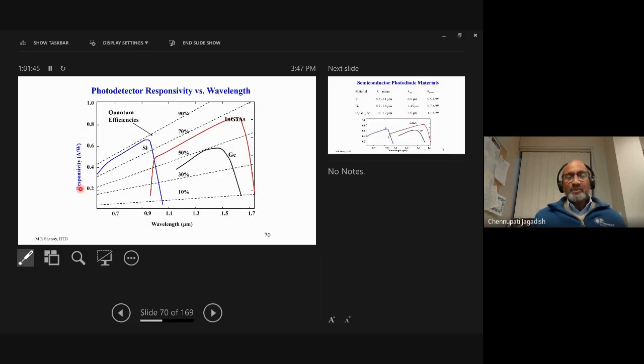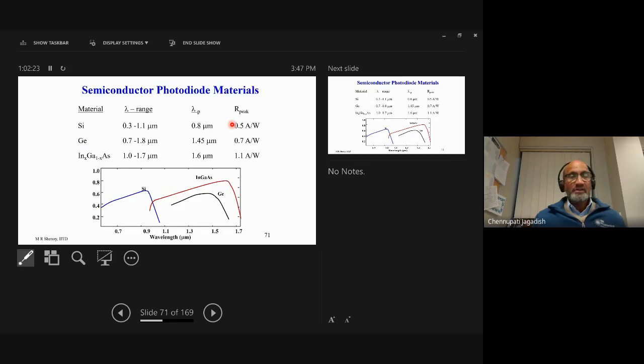So you can see responsivity as a function of wavelength, and silicon is very good from a photodetection point of view. That's one of the reasons solar cells, photodetectors and CCD cells are made out of silicon. But silicon is good from about 0.4 microns, or 400 nanometers, up to about 1100 nanometers or so, and afterwards it becomes transparent because it's below the band gap of silicon. That's where germanium comes in, and then indium gallium arsenide. Indium gallium arsenide is particularly efficient, and that's why the optical communications industry and others use InGaAs detectors, and a lot of spectroscopy people also use InGaAs detectors to detect a wide variety of signals.